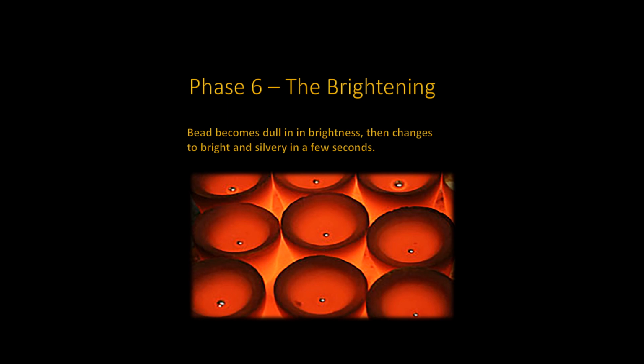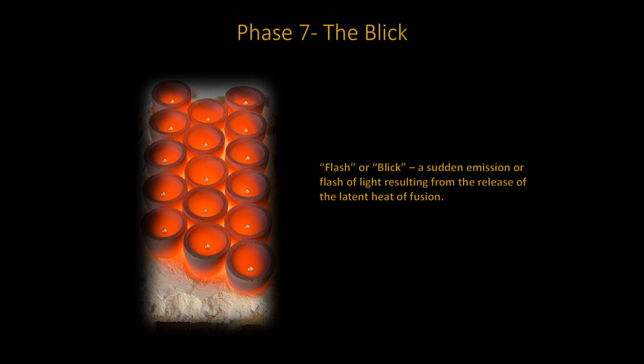This bead has now been transformed from an alloy of lead and precious metals to a bright liquid globule of gold, silver, and if any, a platinum group metal or metals. This globule is now free of any oxide coating that existed. This phase is nearing the end of the cupellation process. The muffle temperature should be above the melting point of this new alloy, free of lead and other oxides. It is time to let this new bead, referred to as a dore bead, cool slowly.